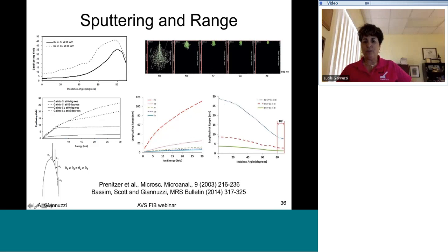But what we also notice is that as we go to low energy, the effect of incident angle on the range is affected by energy. Let me start over, sorry. We take a look at range versus incident angle. At 30 kV, we see a huge difference. The range is going to vary dramatically at 30 kV when we change incident angle, and we can just see that here, right? The range is changing drastically, or the sputter yield changes drastically, and so you can expect that the range changes drastically. As we go to lower energy, the effect of incident angle on range decreases.